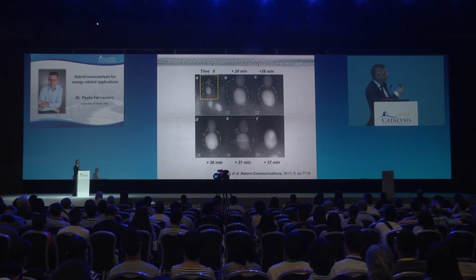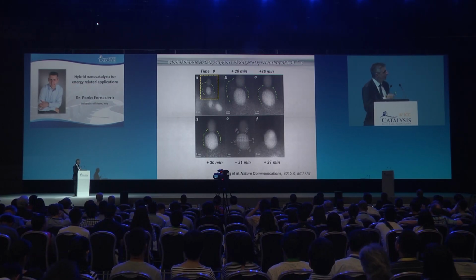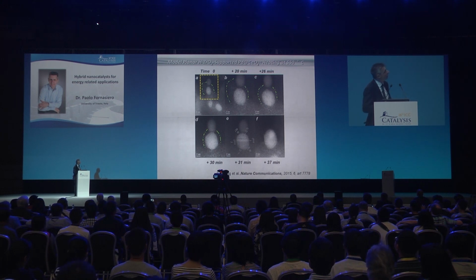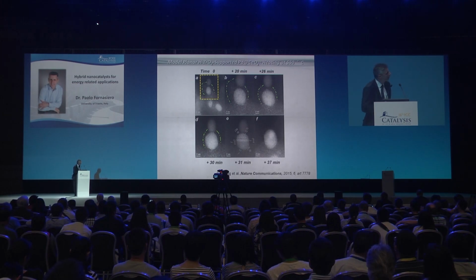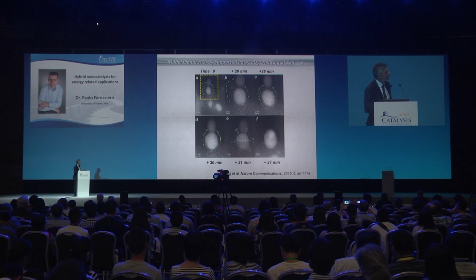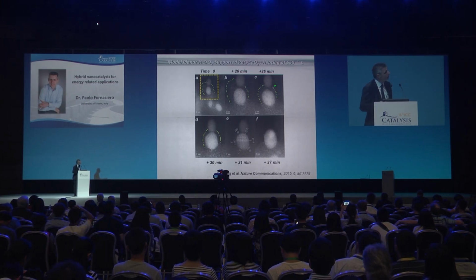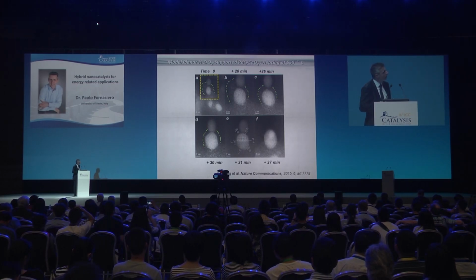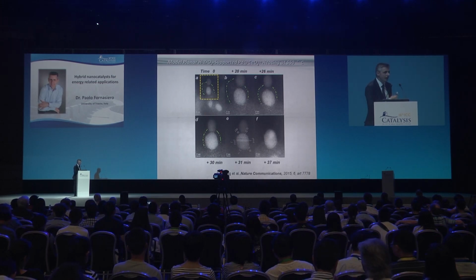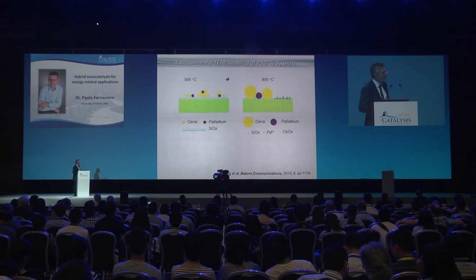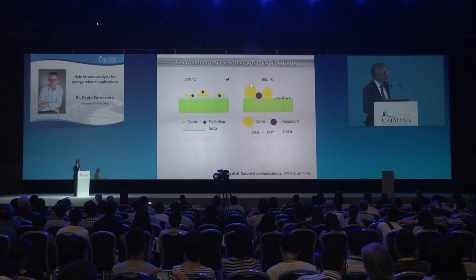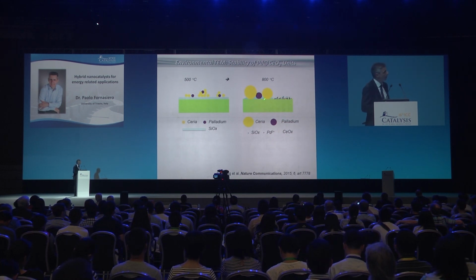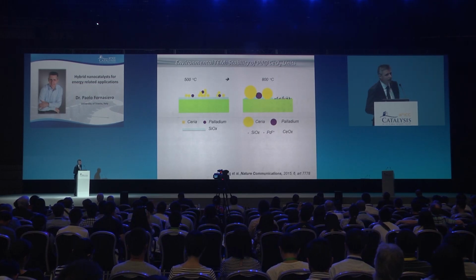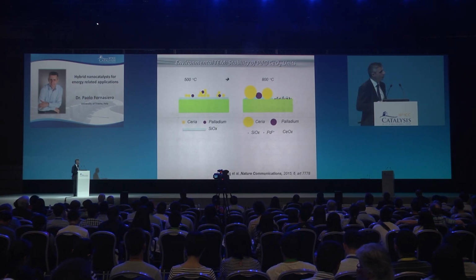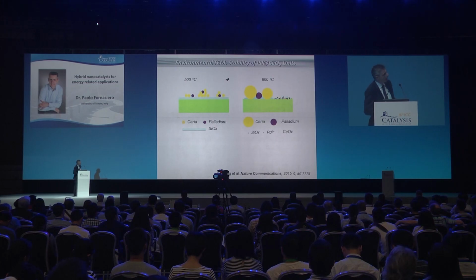Just to mention, there will be a specific talk on Friday on this aspect from colleagues from the University of Michigan. They investigated our palladium ceria material in their very nice environmental TEM, and they pointed out that the system is much more complex than what we thought at the beginning. Indeed, you can observe in these TEM images with time at high temperature, 550 degrees Celsius, that there is a change. These are clouds of ceria atoms that move, so you have a reconstruction, especially at high temperature. You still form some big ceria particles and some large palladium particles, but very importantly, to justify the stability of the activity of this catalyst, many structures remain very small, where you always have palladium in contact with ceria, and silicon can also have a role in improving the redox properties of ceria.